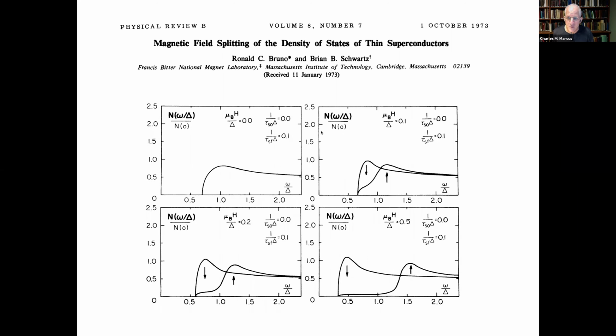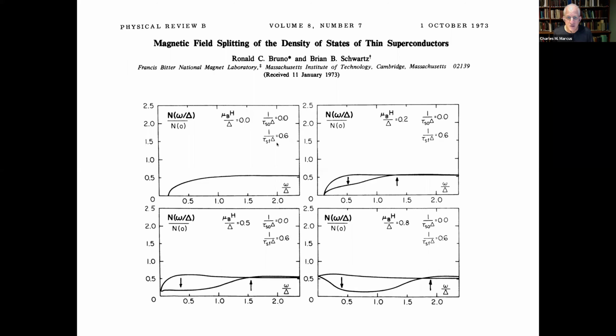Similar situation when you turn on spin flip scattering. Here's mild spin flip scattering. This is a non-zero but small number. Obviously, nothing happens at zero magnetic field except a rounding of the density of states. You no longer have the singularity. They split, but they maintain some degree of separation. By the time you turn on strong spin flip scattering, the same thing happens, including the appearance of gapless superconductivity.